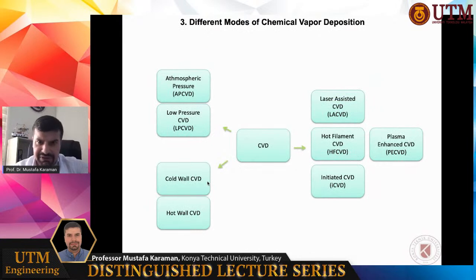CVD is a very efficient technique, and there are many different variants of CVD developed until now, depending on the type of the reactor, the type of the activation energy, and the type of the precursor. Atmospheric pressure CVD and LPCVD are the most general ones. CVD systems are divided into two reactor geometries, cold wall systems and hot wall systems. In the cold wall systems, only the substrate is heated. In the hot wall system, the complete system is heated in a furnace.